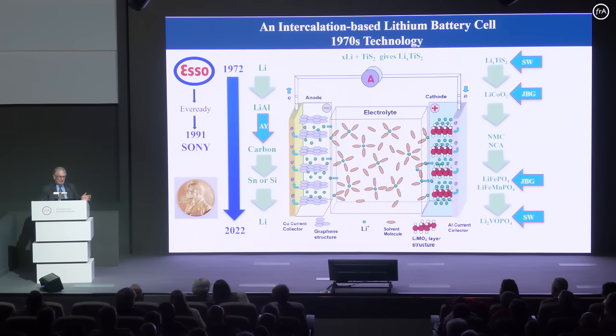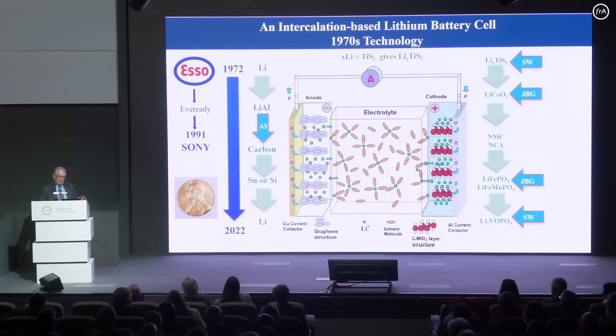On the cathode side, we start out with the layered compound titanium disulfide. John Goodenough, who was at Oxford at the time, read our paper and said, "Oh, the compound I'm working on, lithium cobalt oxide," and he was interested in magnetic behavior, has essentially the same structure. "I'm going to try it." Now, no self-respecting chemist would ever try it. We didn't do it. Bell Labs didn't do it. According to textbooks, cobalt-4 does not exist. So you should not be able to take lithium out of lithium cobalt oxide. John tried it, and it works. And that's what's in all your phones today. It's clearly unstable, and I'll get back to that in a few minutes.